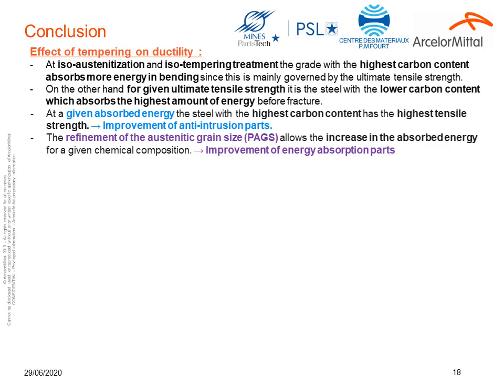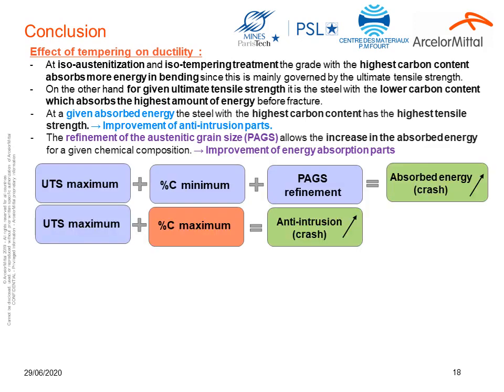The refinement of the austenitic grain size allows the increase of the absorbed energy for a given chemical composition, and this could, on the other hand, improve the energy absorption part. In summary, we are looking for an ultimate tensile strength which is maximum, with a carbon content which is minimum, together with grain size refinement to enhance the absorption energy part in a crash.